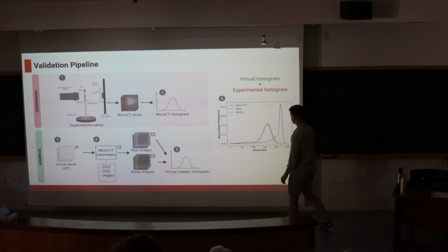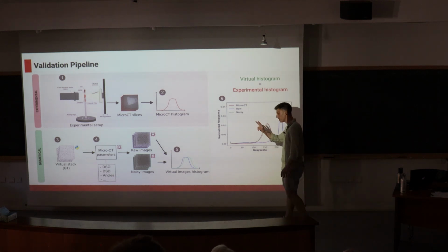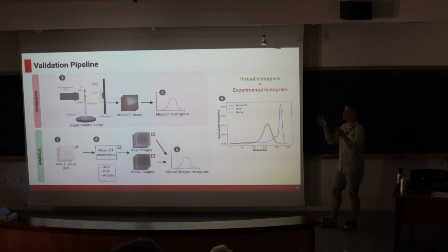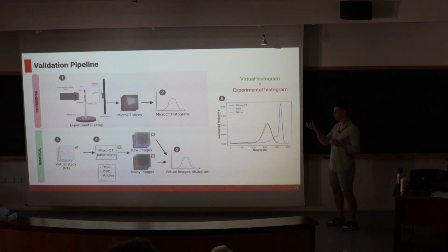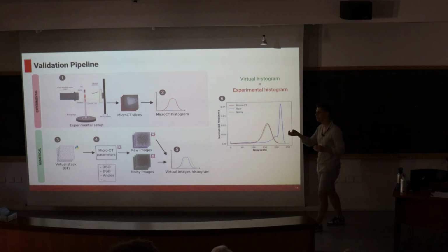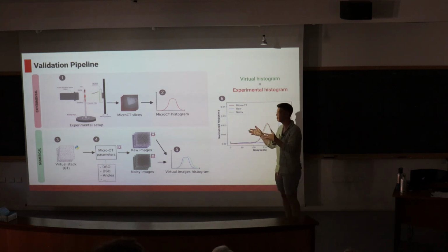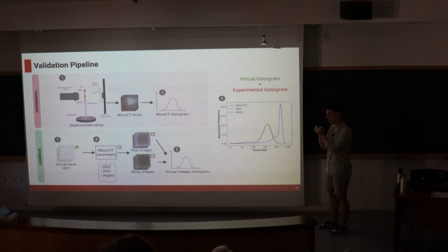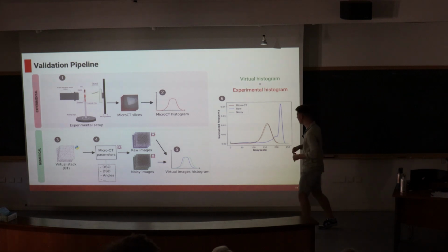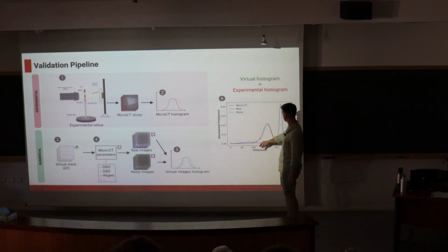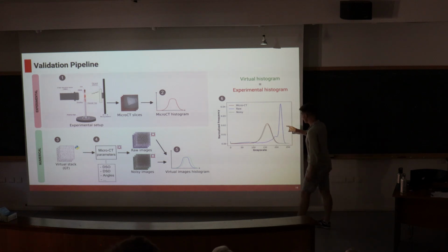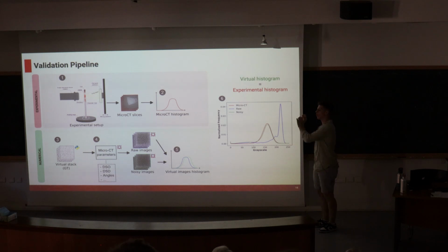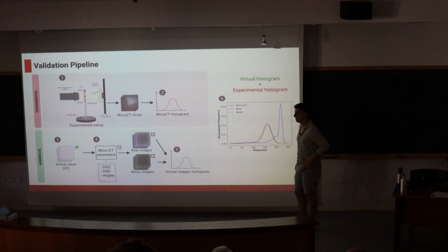So yeah, actually this is due to two things: the fluid inside, because during the microCT, okay, this is not in air. I put some fluids inside. This is called DMEM. It's like PBS, okay, so saline solution with glucose, etc., nutrients, in order to keep the sample wet. This is very important, okay. This is due to this first one, and the second one is due to the stain, because with this stain it is very complicated sometimes to distinguish between porosity and the tissue. This is basically due to these two things. So it's fully saturated. Yeah.